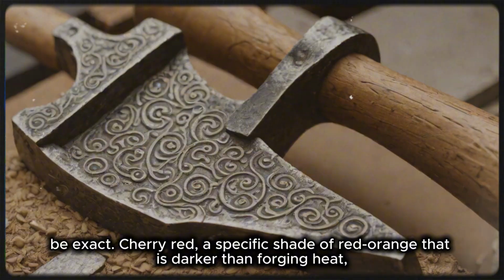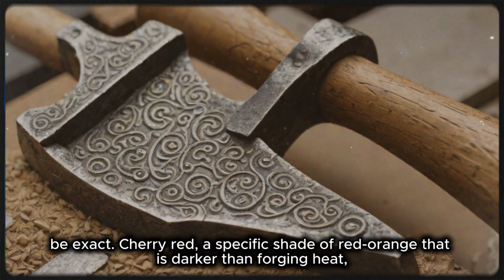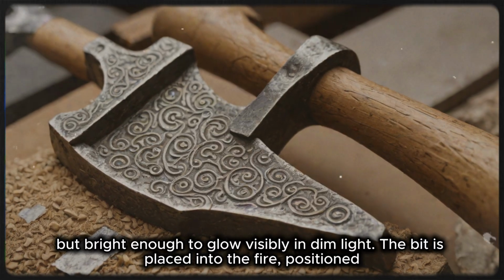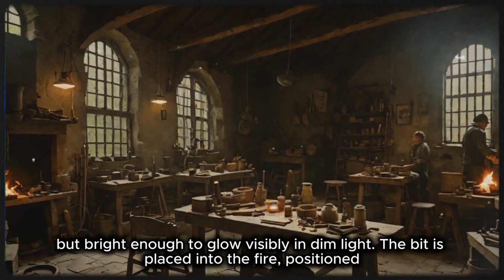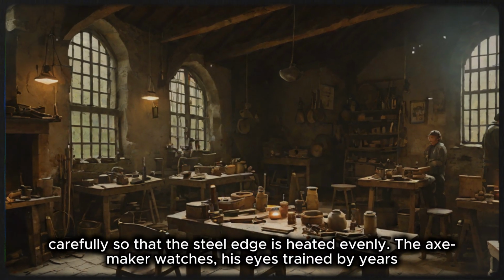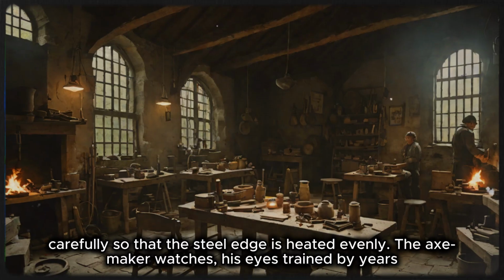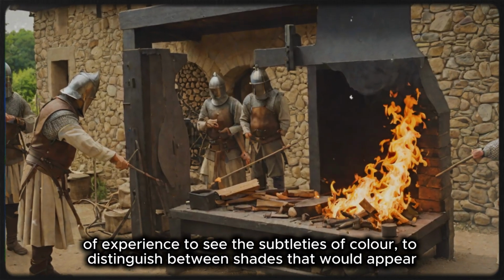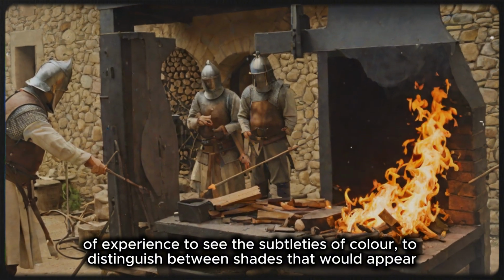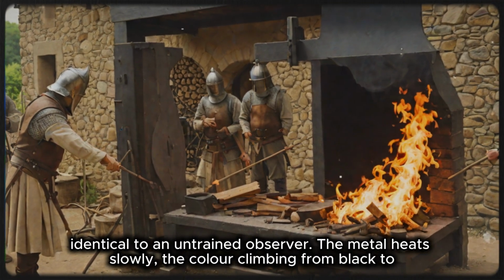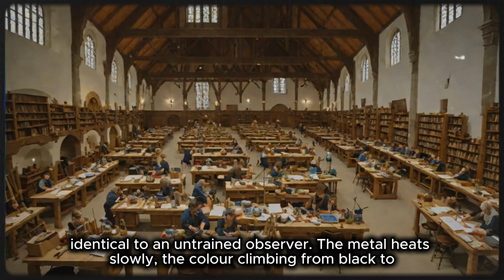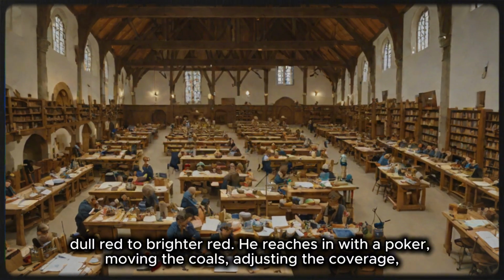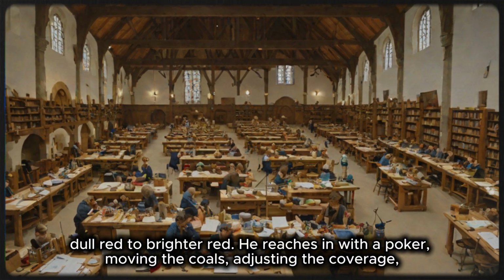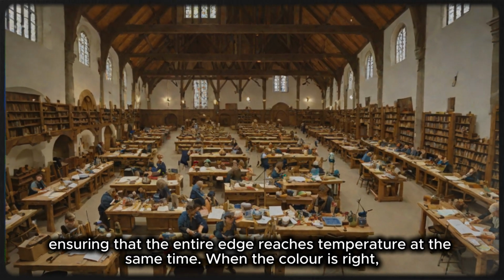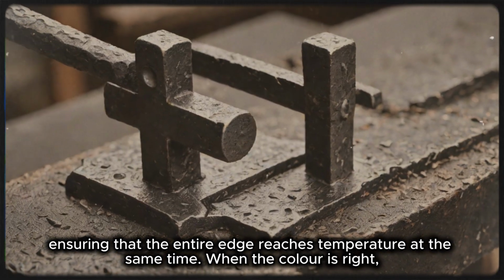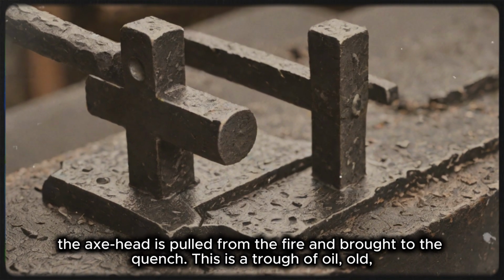Cherry red, a specific shade of red-orange that is darker than forging heat, but bright enough to glow visibly in dim light. The bit is placed into the fire, positioned carefully so that the steel edge is heated evenly. The axe maker watches, his eyes trained by years of experience to see the subtleties of color, to distinguish between shades that would appear identical to an untrained observer. The metal heats slowly, the color climbing from black to dull red to brighter red. He reaches in with a poker, moving the coals, adjusting the coverage, ensuring that the entire edge reaches temperature at the same time.